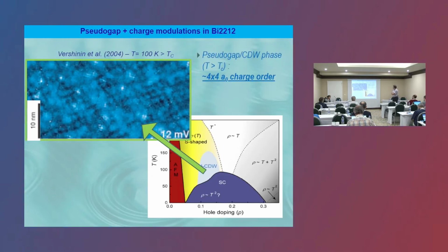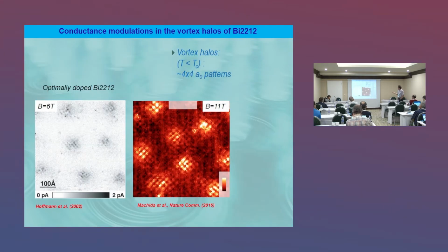Now, BSCCO also has this vicinity of charge orders. This is an example of underdoped BSCCO where some modulations were detected by STM. So this is part of the phase diagram. These modulations were taken in the pseudogap regime and linked to the charge density wave. And similarly, as I already told you, the vortex halos also are usually the sites where charge modulation or conductance modulation are detected.